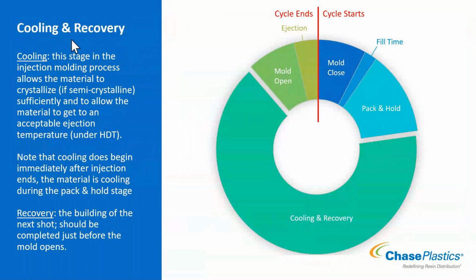From there, the cooling timer will start. Once pack and hold is done, we start cooling. Cooling and screw recovery, building the next shot, happen concurrently. You may often use a delay before recovering the screw so that the material isn't sitting at molten temperature for longer than necessary. However, there is one thing to note and to think about. The second the material is forced up against the mold wall in the pack and holding phase, we have technically started cooling.